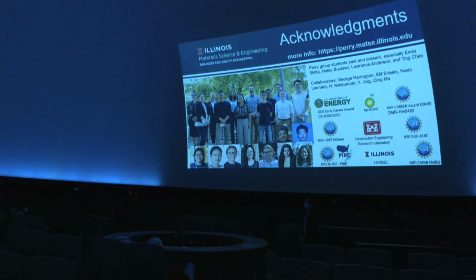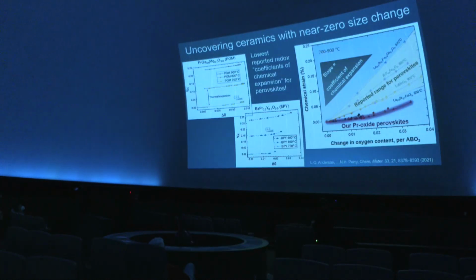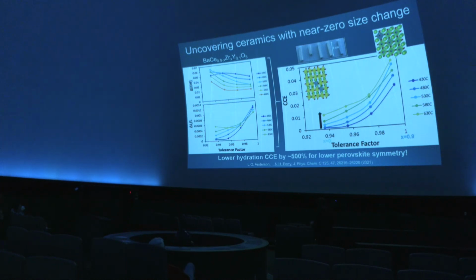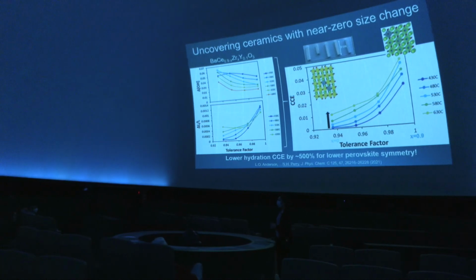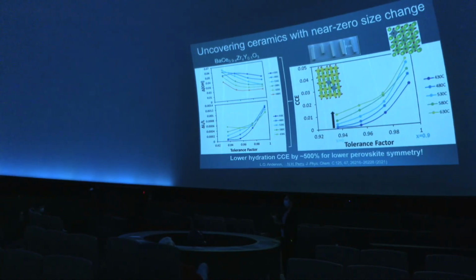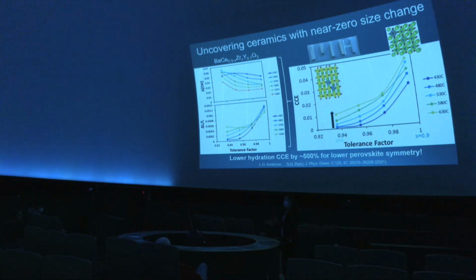Why does symmetry in the lattice decrease durability? Decreases it. Yeah, so let me see if I can. Oops, I went too far. This one, yeah. Right, so the symmetric structures were giving really high coefficients, which means these materials, when they're symmetric, and they give oxygen out, or they take, in this case it's hydrating, so it's bringing water in. When they're symmetric, they do expand a lot when they bring in the water. Why that happens is actually something we're still looking at. We just hypothesized that this was the case. We tested it. We found that correlation exists.